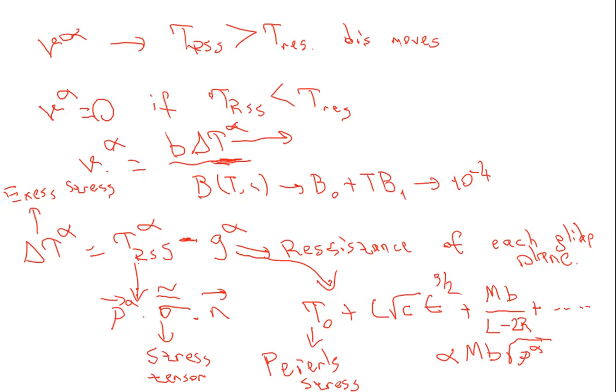So if we add more strengthening, we are increasing G. So if we produce more dislocation, for example, we are increasing the dislocation density, or if we add more solute, we are increasing the solid solution strengthening effect, then we are increasing the resistance of each plane. In order to overcome this resistance of each plane, we have to increase our resolved shear stress, right? Then we have strengthening. So that is the mechanism.